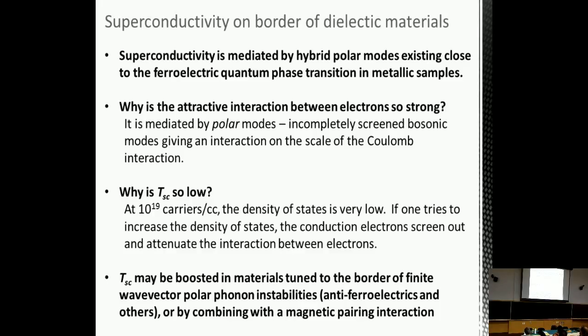But Tc may be boosted, we think, in materials tuned to the border of a finite wave vector polar phonon instability, such as antiferroelectrics or quadrupolar, higher-order types of states, or by combining this interaction with a magnetic pairing interaction.